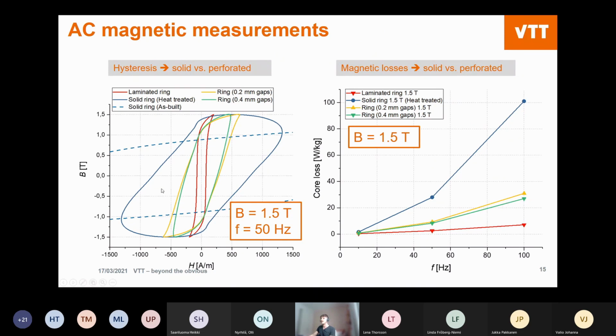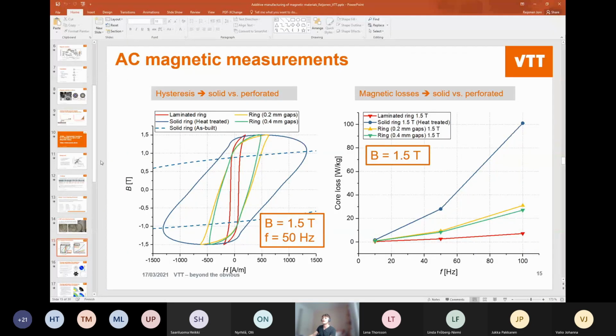And then on the left-hand side, you can see the coercivity and the remanence. The red one here, a narrow loop, would be the ideal. This is the conventional material. Here in blue, you can see the solid printed material without the holes. So not what we want. Then with the holes, we were able to reduce the coercivity quite significantly. We had 2 hole sizes. There wasn't a big difference between them.